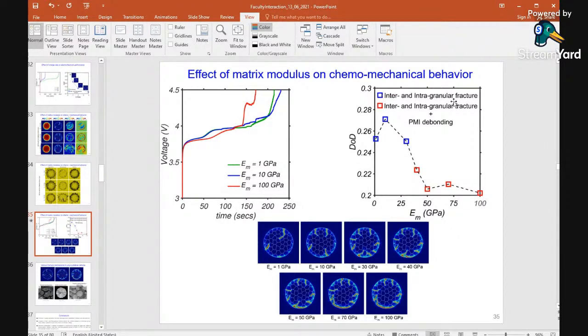We can see intergranular fracture is happening up to 25, and then we have a very mixed fracture, intragranular and particle debonding. You do not anticipate particle debonding at first. Okay, so that is coming after the hard material, the hard binder. So that is coming after.